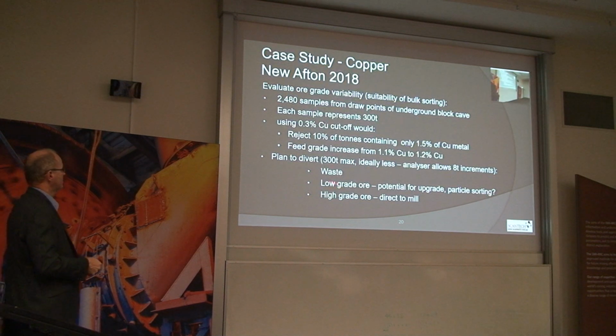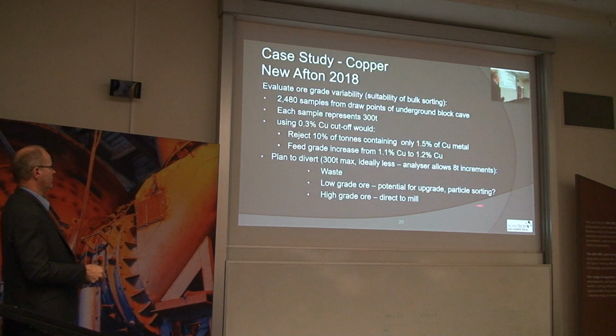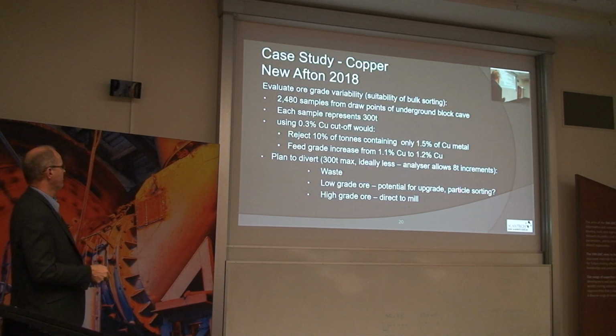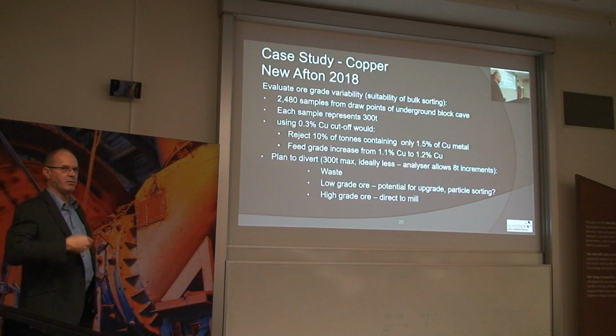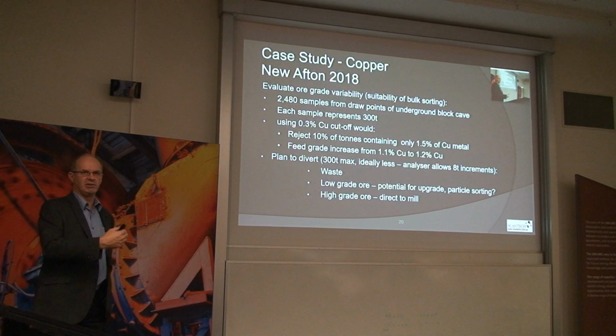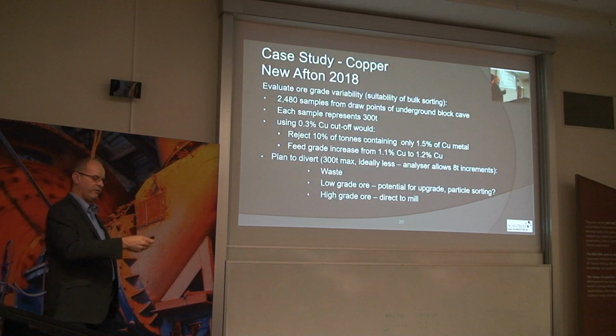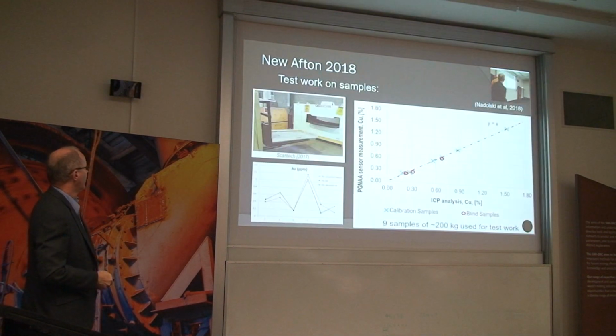Initially they planned to divert waste, low grade, to particle sorting, which was still to be assessed further, and then the high grade would go direct to the mill. That was based on a 300-tonne decision. What we're giving them is every 8 tonnes. So we're giving them a much higher level of selectivity to base their bulk diversion decisions on.